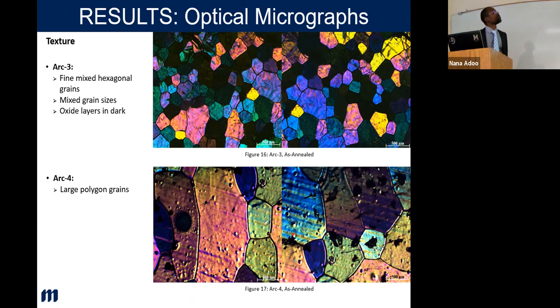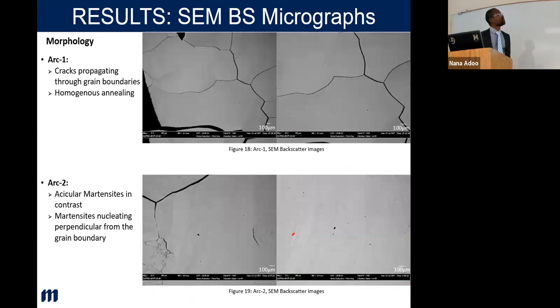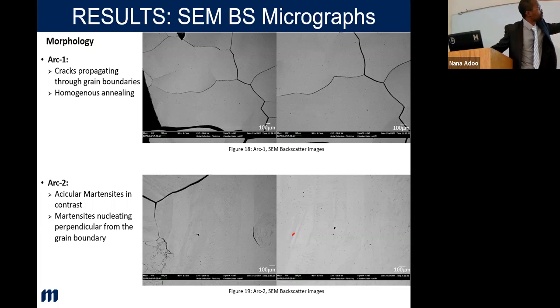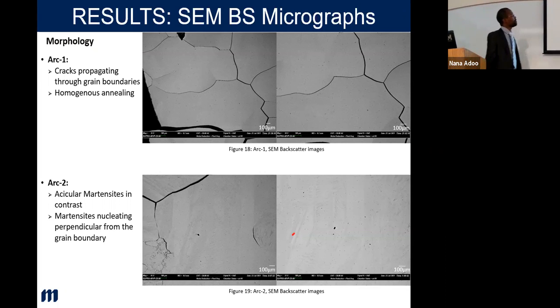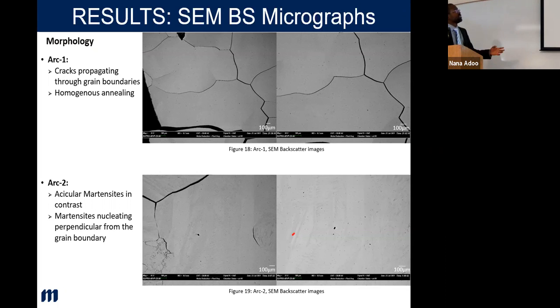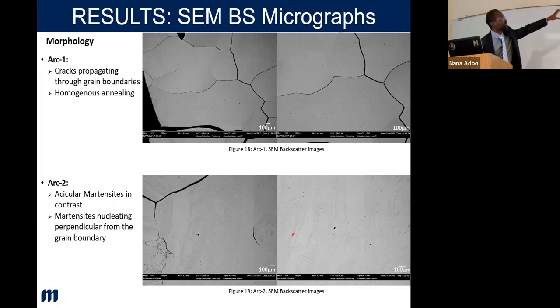And then the one that transformed showed this one as annealed. To go further into it and try to figure out what was happening, I did a backscatter image analysis, which is by the EDS, by the SEM. Try to get you contrasting images based on atomic number differences. So large atomic numbers will actually appear bright for you. So you could see in arc 1 that there is homogeneity in the sample. You could see the phase grain sizes and then everything matching out there, same.